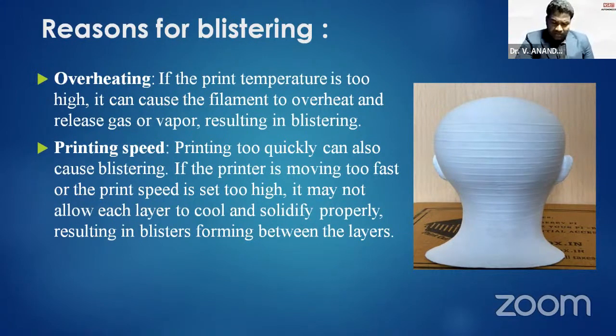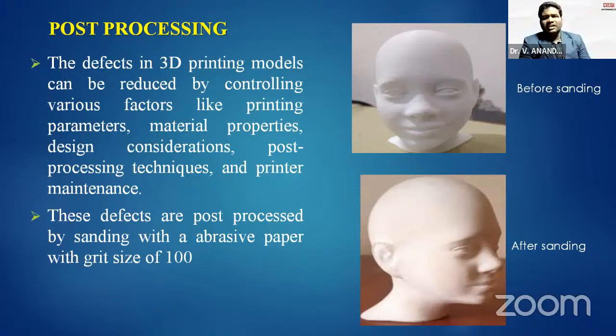So they identified the reasons why this blistering and these cracks happened on their face models, and later they decided to do post-processing. They finally sanded their bust models. The top picture shows the bust model of one student before sanding, and the bottom figure shows the same bust model after sanding. We can see the difference between these two models. In the top model, we can see some warping and blisterings on the face, and after sanding, those are avoided.